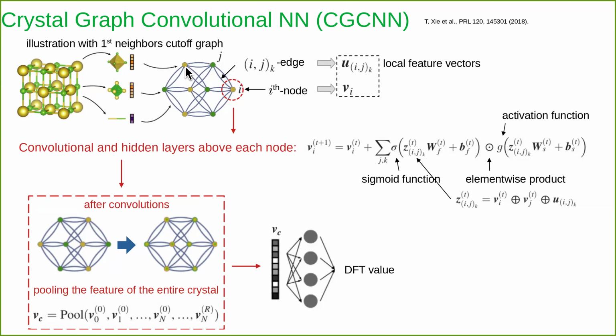So each atom or each position will form a node, and in between the nodes you will have edges, the distances or bonding, the first order binding. Both features will be stored and represented in a vector. The nodal information is simply related to the chemical element, so hydrogen would be the 1, 0, 0, 0, 0 vector, and helium will be the 0, 1, 0, 0, 0 vector. Meanwhile, the distances will be stored with the help of several shifted Gaussian functions, sampling the Gaussian distributions according to the distances in your crystal.